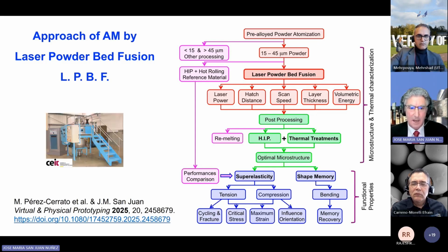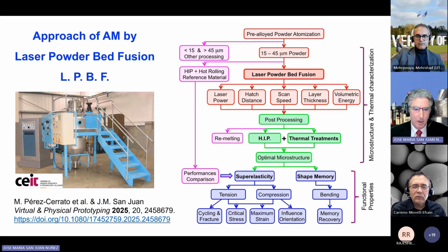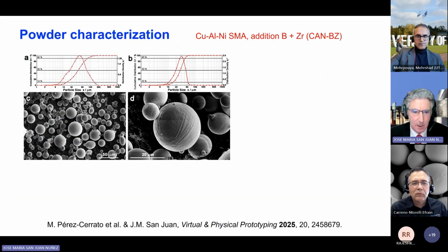As I commented, it all starts with the powder atomization that is done by our partners at CEIT, who have a small atomizer that produces 3 kilograms per atomization. And then these are the kinds of powders we get. This is the complete distribution, and after sieving from 15 to 45, this is the distribution we have. You can see here a powder whose transformation temperature is above room temperature, so you can see the martensites in the powder particle. And as I commented, the atomizer produces 3 kilograms in each atomization.